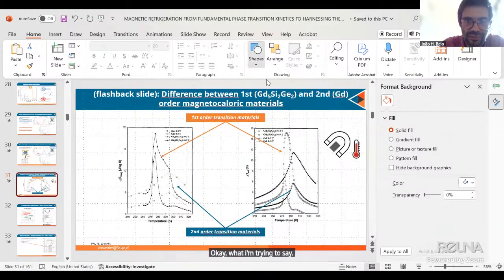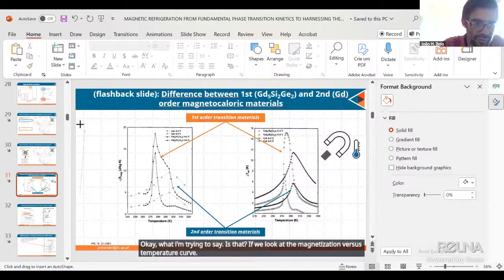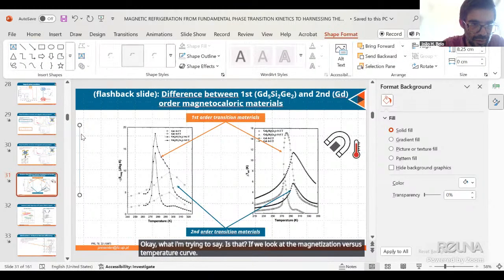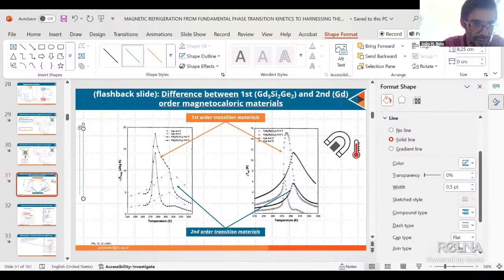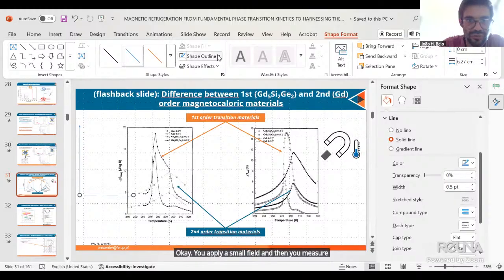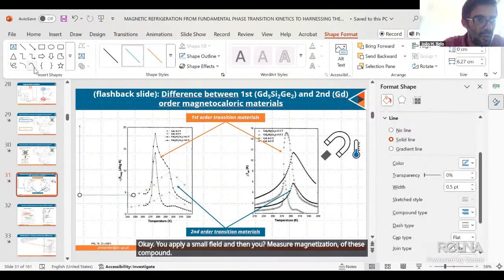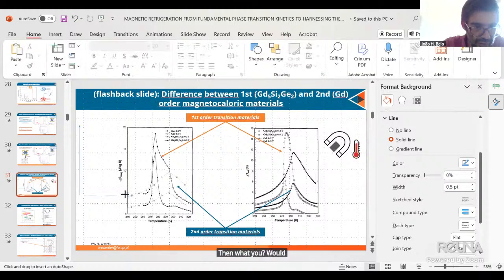Okay, what I'm trying to say is that if we look at the magnetization versus temperature curve, you apply a small field and then you measure the magnetization of this compound. Then what you would observe is something like this.